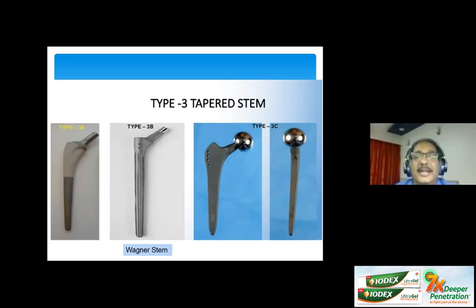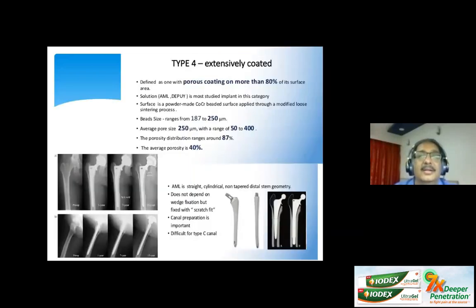The Wagner cone stem I will come to in a minute. It is a shorter version and gives you good options. The type 4, the extensively coated stem, was the AML, and now it is the Solution stem. The Solution stem is more or less used in revision scenarios or in certain complex scenarios where we need a distal fixing stem of a longer variety. They are not good in Dorr type C canals, as Atul alluded to, because the quality of cortical bone is extremely poor there and they don't have much hold. They depend on a scratch fit and are technically, again, very demanding if used.